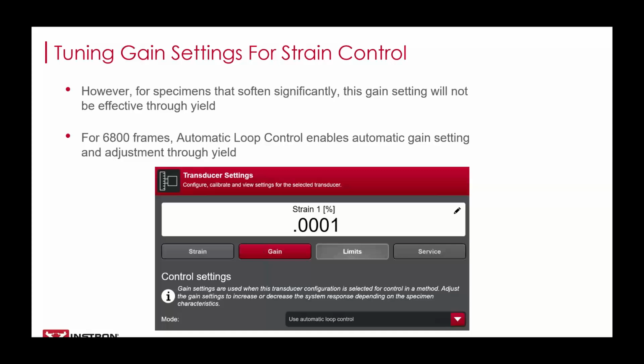This feature is especially useful if you're testing different alloys. Nickel alloys such as Inconel 718 or 625 have a much more pronounced decrease in stiffness through yield than ferrous alloys like 4340 or 300M. By using automatic loop control, you can follow your same test parameters, not only from specimen to specimen of a single alloy, but you can also accommodate the difference in behavior from one alloy to the next.